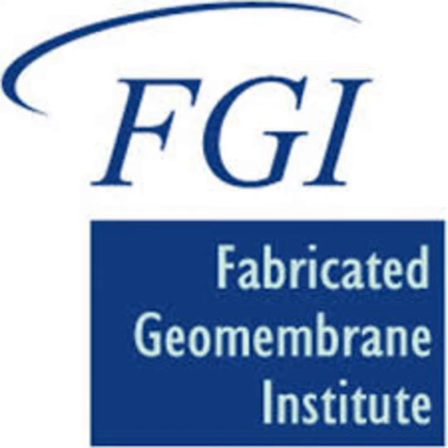Yeah, you hit again the high points there, Chris. On the blown film side, the texturing, there's an ASTM test method to measure the height of the asperities of the texturing, and that's really important. It's not the topic of this webinar, but certainly no asperity height should be specified less than 15 mil, in my opinion.